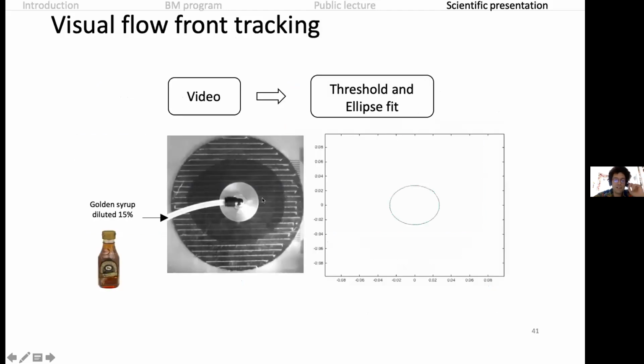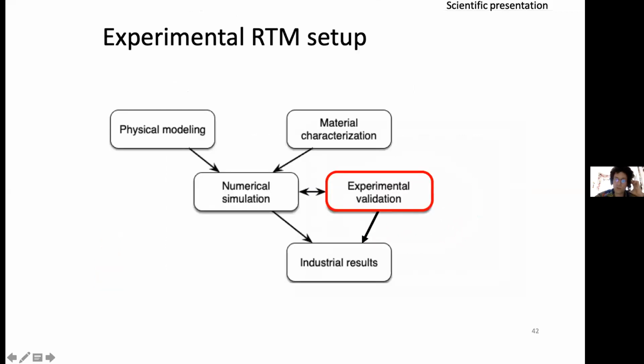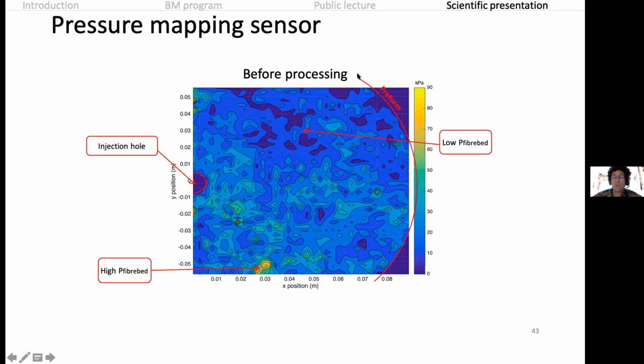And you see that here, typically, with a video camera, you can see when we inject the resin. So here we took some golden syrup just for the test case in the lab, and we injected some fluid, and we see the dry part of the preform and the wet part of the preform. So we can see the flow front. If we do some image analysis with a computer, we can actually identify this flow front, which is an ellipse in this case, and this gives some visual information on the flow front location. At the same time, and we are here working on the experimental part, you understood that, I hope.